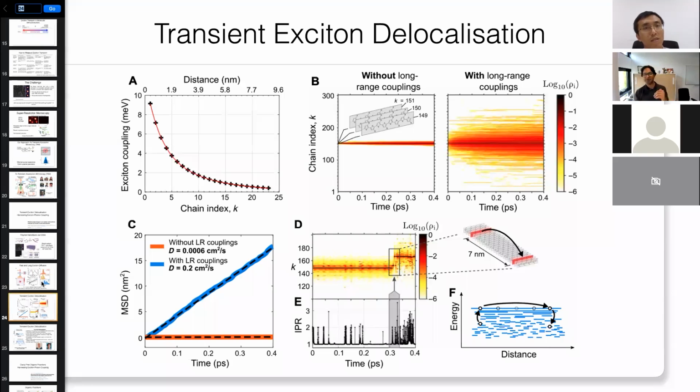So the vibrations are very key here. This kind of trick can only be possible in organic systems, which have these high frequency vibration modes, conformations, torsions, etc., which can lower the energy such that the localized state is actually lower in energy than the delocalized state, which from a fundamental, normal quantum mechanics picture, you would think is the opposite way around. But that's because the molecules are changing shape, so they actually change the state of the system. It's a completely different quantum state than the fully delocalized, structurally rigid polymer or whatever system. So the system itself has changed. What should have been the lowest energy delocalized state is actually higher in energy. And that's again a trick you can only play with organics. You can't do this in gallium arsenide or any of these systems. That's a beautiful thing about organic materials: you can do lots of quantum mechanics which are not accessible in inorganic systems. So these systems still have a lot of tricks to teach us.